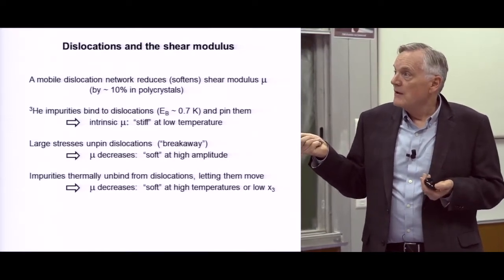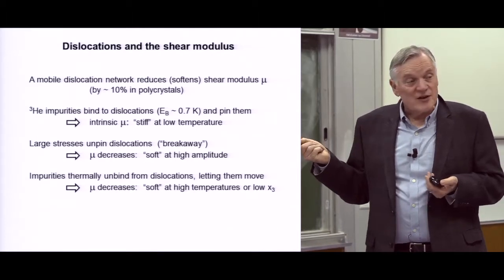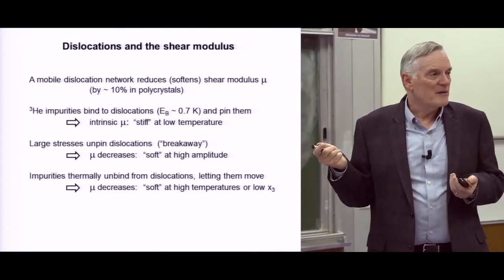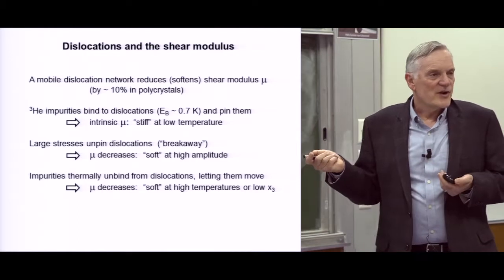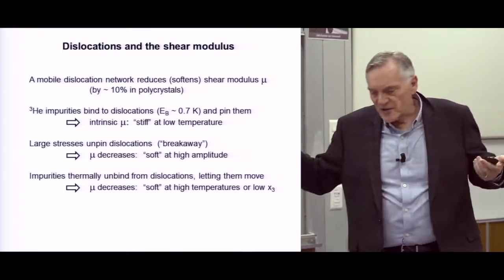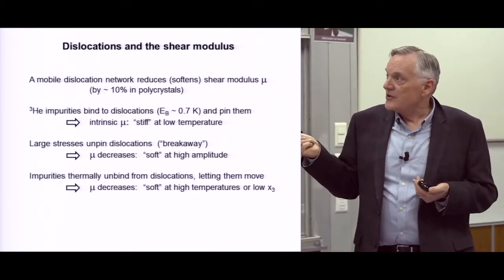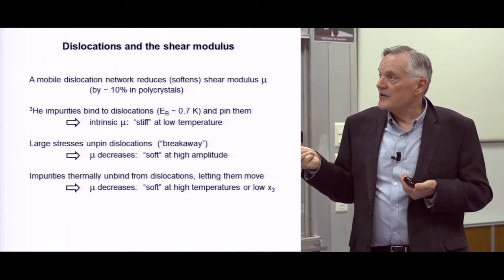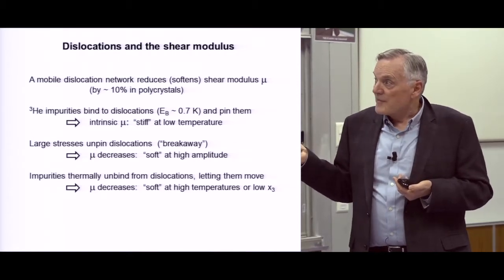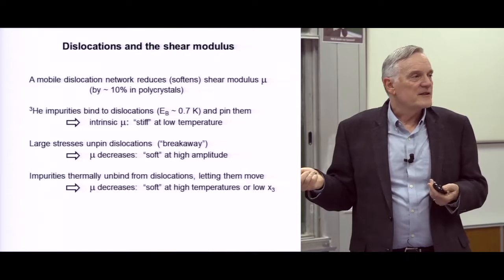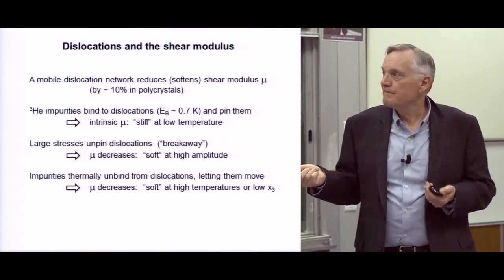As you input large stresses on them, helium-3 are not a very strong pinning point. It's not hard to rip the dislocations away from them. So the stress exerts a force. They rip away. And that explains the amplitude dependence. It's always soft at high amplitude. And as you go up in temperature, they just leave. They boil off the dislocation and become soft again.